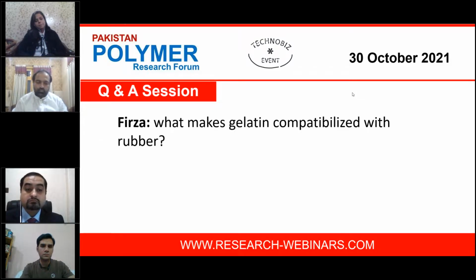So what makes gelatin compatibilized with rubber? As I already discussed, the first factor is I have introduced gelatin in NBR rubber. NBR stands for nitrile butadiene rubber that has an acrylonitrile compound present in it. That makes it a polar rubber. Along with this, gelatin is also a polar material that makes polar interaction increase. Furthermore, for better compatibilization, I have added silica that is surface treated with a silane material that increases its compatibility and bond strength. These two factors make the gelatin compatibilized with rubber to have high mechanical properties.